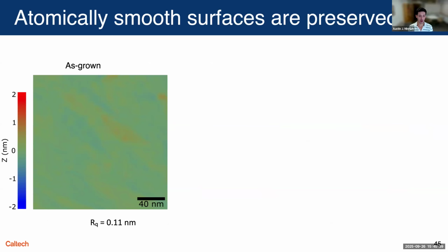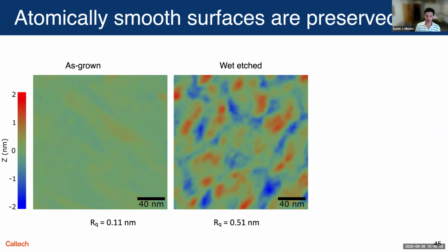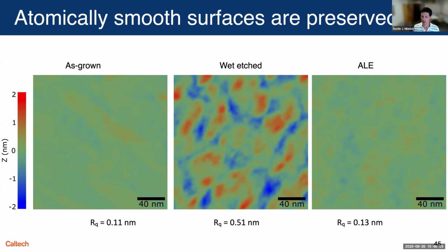So finally, we want to look at the surface characteristics of the etched surfaces. On the left is the AFM scan of the as-grown wafer, which is very, very good, an RQ of 0.1 nanometer. This is after wet etching a few nanometers of the semiconductor, and you can see it's clearly rougher. And this is after ALE of order 100 cycles or so. And you can see it's essentially indistinguishable from the as-grown.